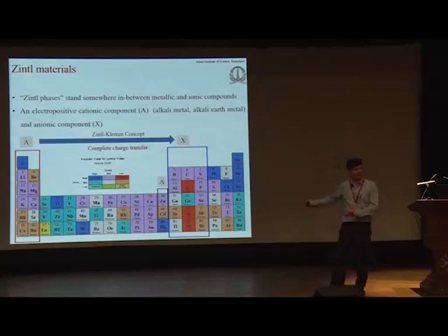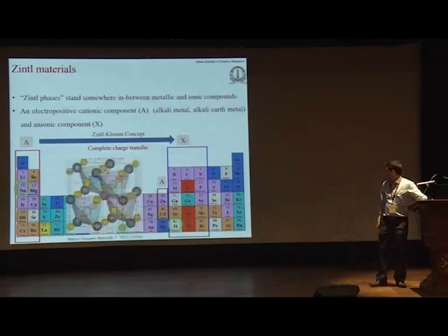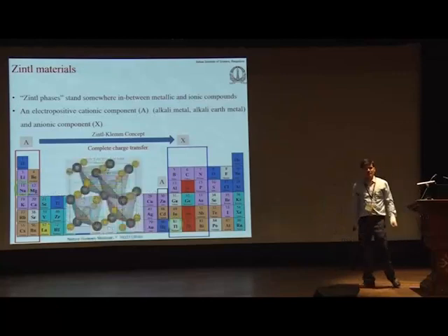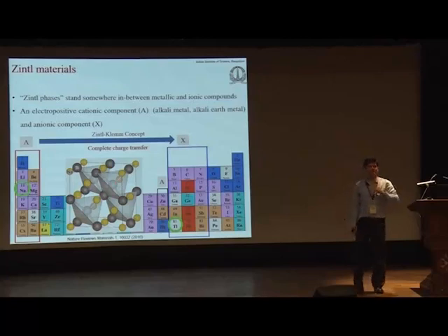And because it got 14 electrons, it forms a tetrahedral network of the thallium itself, and the sodium goes in between. So the structure becomes very interesting. Here is the structure. So sodiums are hanging there. They work as a scatterer or as a rattler for the phonons, and the electrons can go through the lattice of the thallium.